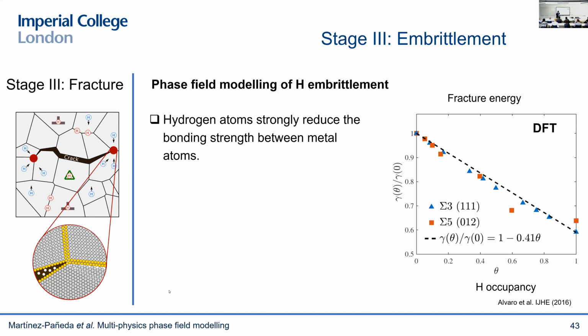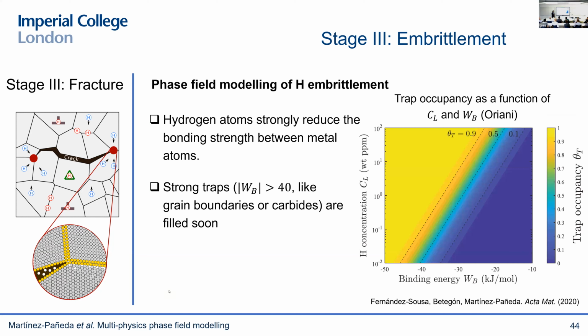And then the question is, okay, but how much hydrogen do we have, right? Because if we are somewhere here, then, well, some of the mechanisms might be playing a role. And the answer to that comes from the experiments and from the thermodynamics of trapping. We can use what is called Oriani's equilibrium to relate the hydrogen concentration in the lattice with the occupancy of that interface, of that grain boundary, and with the binding energy, which is a property that measures how energetically favorable it is for the hydrogen to sit into that interface, that grain boundary, for example.